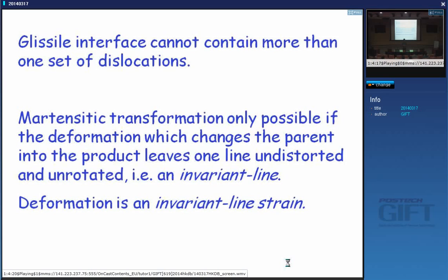No, I think it's the relationship between the two. So for example, in copper zinc, you get a transformation from BCC to FCC martensite. Whereas in steel, you get from FCC to BCC. Actually, even in steel, you can get the reverse transformation happening like martensite. So if you take your BCC and you heat it very rapidly, then it will undergo martensitic transformation to austenite.